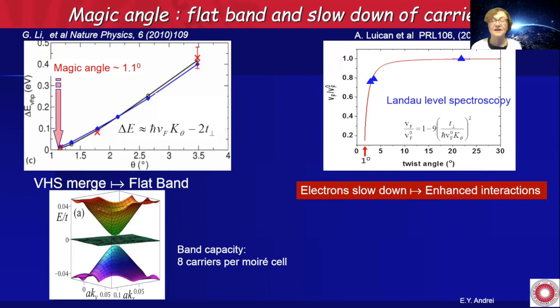Now we can also measure the Fermi velocity, because when you reach such a flat band, clearly you've kind of stopped the electrons dead in their tracks, and now they can interact, they see each other. So we wanted to measure the velocity, and we managed to measure about 3 points using Landau level spectroscopy. We saw about an 80% decrease in the Fermi velocity. We couldn't go any further here. But fitting into theory, this shows that as you go to the magic angle, not surprisingly, the velocity just goes to 0.